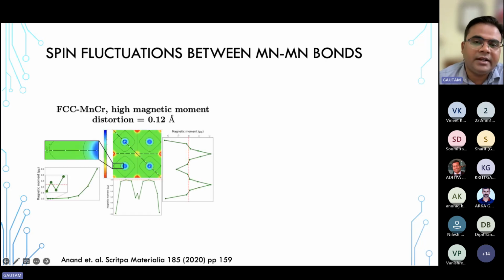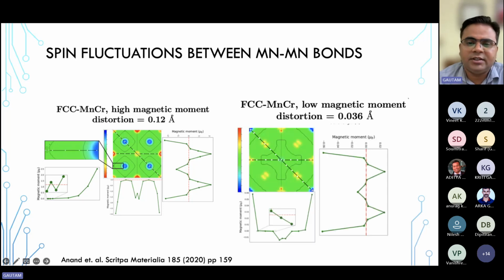So what is happening here also? We studied the spin fluctuation here also, and we found that in a case where you have a high magnetic moment and a high distortion, the fluctuation in the magnetic moment is taking place. We scanned it in real space and we found those fluctuations. And in the case where there is limited distortion, these fluctuations are not there.